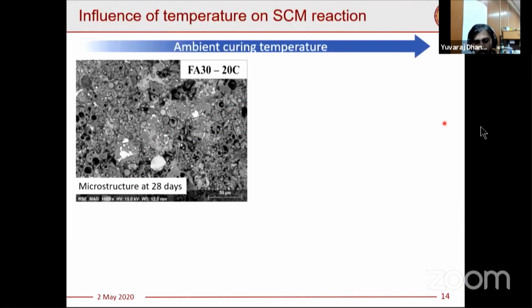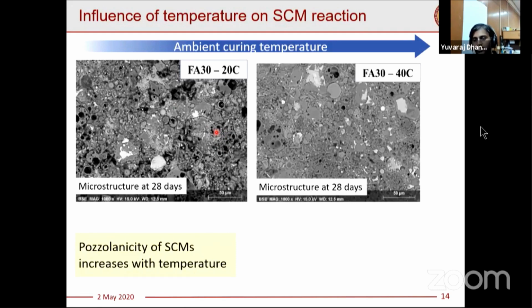So what are the other impacts? Like, for instance, the role of temperature. This is a microstructure of a fly ash cement, which is reacted at typical laboratory conditions at 20 degrees Celsius. The spherical particles which you see here are all unreacted fly ash particles, which will react in due course of time. When the same system is allowed to react at 40 degrees Celsius, you can see a much more compact and dense structure, because the pozzolanicity of the SCM is accelerated.